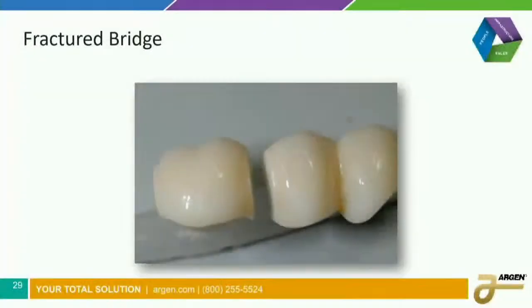Okay? And then we see something like this. When we see fractured bridges like this, it's not because there was too much stress applied to it, but what we find is that these are the results of people trying to get a little too aggressive with a hard diamond disc, trying to open up the embrasures. Now I know why you're trying to open up the embrasures, because zirconia generally doesn't look as good as dental porcelain does. And when you have dental porcelain, you can make a very nice separation between units. You just take your knife and you slice right in there in the interproximal area, and you can't do that with zirconia. I understand why some people do this, but you really shouldn't.